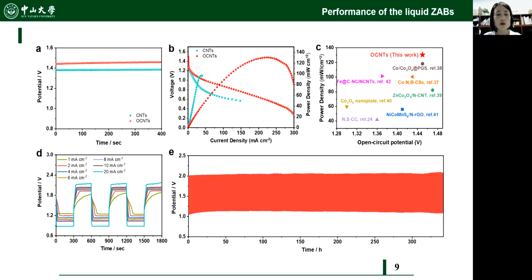To exemplify the feasibility of CNTs and OCNTs for practical application, we assembled liquid zinc-air batteries by using CNTs or OCNTs as the air cathode. The zinc-OCNT batteries showed a high open circuit voltage of 1.45 volts and a superior power density of 113.5 milliwatts per square centimeter, outperforming both the zinc-CNT battery and most recently developed ZABs.